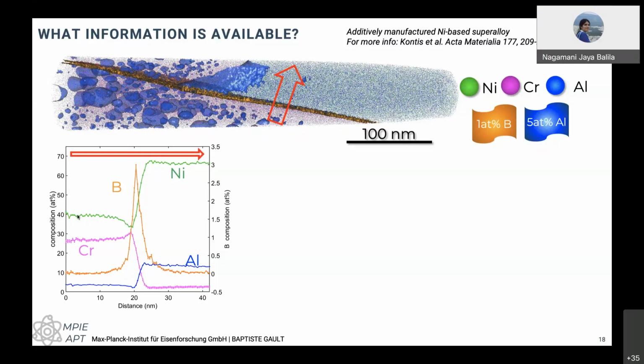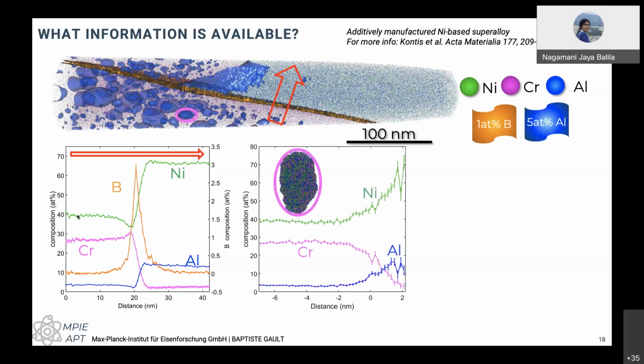And you had another figure after that to get the composition of a precipitate particle. Yep. So that is through another way of scanning the composition, or is it? Yes, exactly. So here you can see I have superimposed on the point cloud a series of voxels that are 1 by 1 by 1 nanometer. And in each of these voxels, I'm calculating the composition. And then I'm joining voxels that have the same composition. So here the blue surface basically delineates regions that contain more than 5% aluminium. So here I can see a lot of smaller gamma prime particles within gamma.